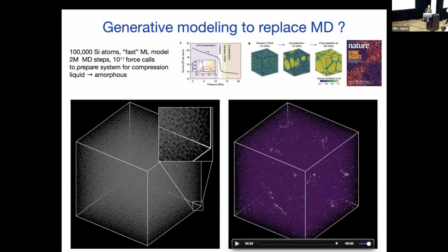Do you train your diffusion model using just squared error on the scores that you're getting from the energy function? Yes. This diffusion model was trained in the traditional way diffusion models are trained, on small examples of amorphous carbon, and then that's the generation step. And that's so terrible that then we did a healing step in which we locally relax using the energy model. But that's not really right. I should be training using the energy function, but we don't know how to do that.